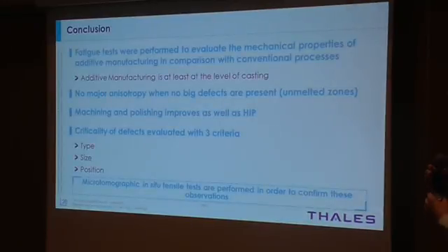To finish, so the fatigue tests were performed to evaluate the mechanical properties of additive manufactured specimens in order to build real parts that will be in our products. And additive manufacturing is at least at the level of casting, so it's a good result for us. There is no major anisotropy when no big defects are present. Machining and polishing improves the fatigue properties as well as HIP, and the criticality of defects were evaluated with three criteria: the type of defect, the size of defect, and the position of the defects.